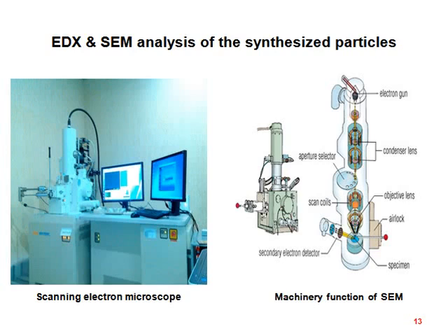Modern SEM generates data in digital formats which are highly portable. The SEM photographs are taken with an average magnification of 30,000 times and 5 to 15 kilovolts at room temperature. The study of the SEM images shows the clear size and shape of CNTs and other nanoparticles as well as the field matrices.